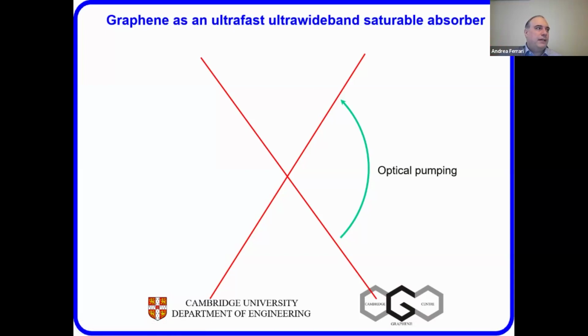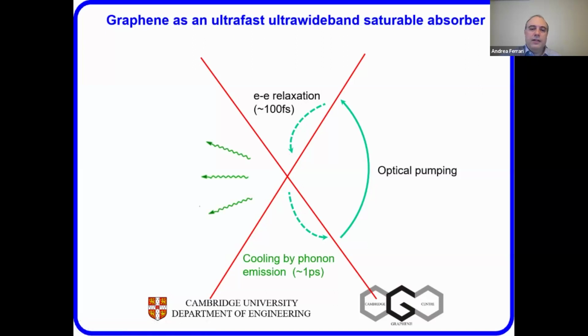So what happens after the optical excitation? You create an out-of-equilibrium population of electrons, and this relaxes towards the ground state. I wrote here 100, but in reality we know it's more like 20 to 30 femtoseconds. And you can also have cooling by phonon emission, but that happens on a picosecond time scale.